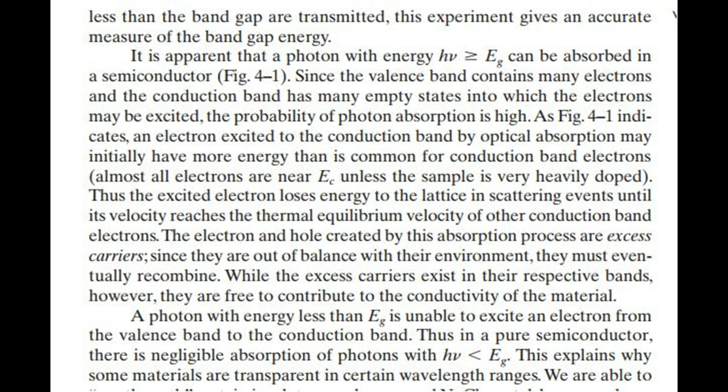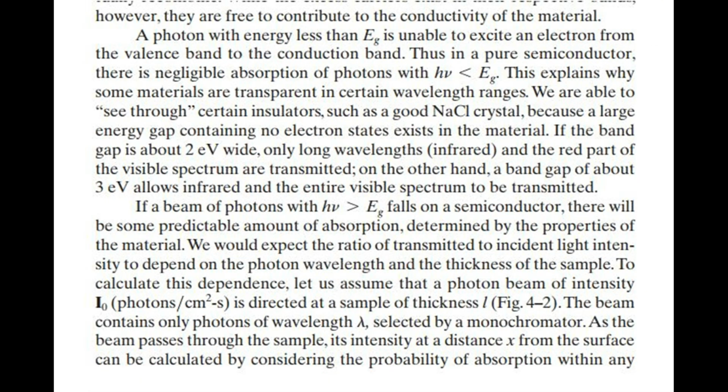We are able to see through certain insulators, such as a good sodium chloride crystal, because a large energy gap containing no electron states exists in the material. If the band gap is about 2 electron-volts wide, only long wavelengths, infrared, and the red part of the visible spectrum are transmitted. On the other hand, a band gap of about 3 electron-volts allows infrared and the entire visible spectrum to be transmitted. If a beam of photons with hν > Eg